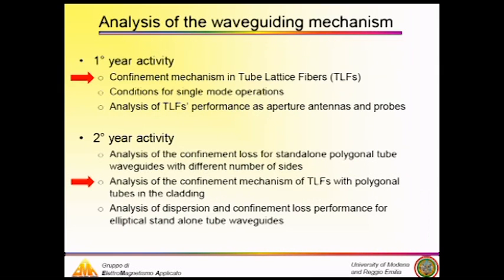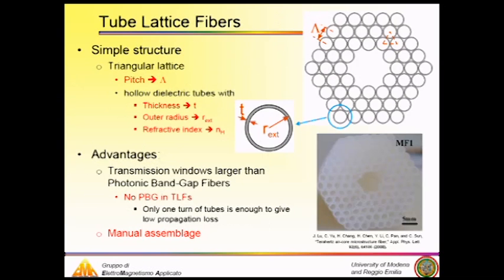This is a short summary of the activity I've done during the first 2 years. Due to lack of time, we are going to simply consider the waveguiding mechanism for this kind of optical fibers. The structure is very simple. The cladding is formed by a triangular arrangement of hollow dielectric tubes. Each tube has its own physical and geometrical dimensions, of course, and the core is formed by the removal of the 7 innermost tubes. The advantage of this fiber is that it has a wider transmission bandwidth than photonic bandgap fiber, and since there is no photonic bandgap, it requires only one ring of tubes around the core, and this gives a more compact waveguide with respect to photonic bandgap fibers. Another important aspect is that they can be assembled manually, which is, of course, very interesting.